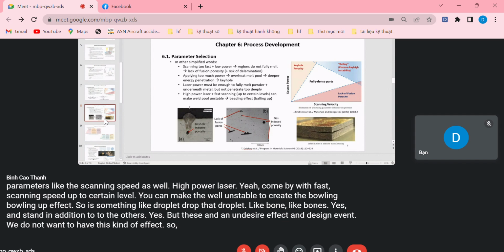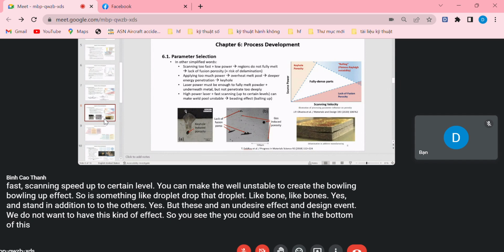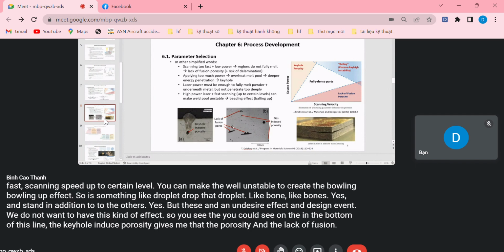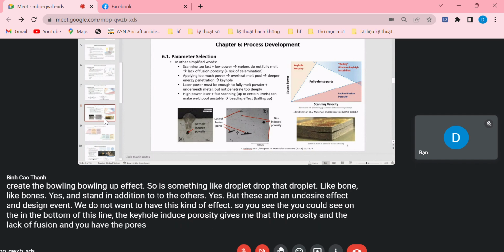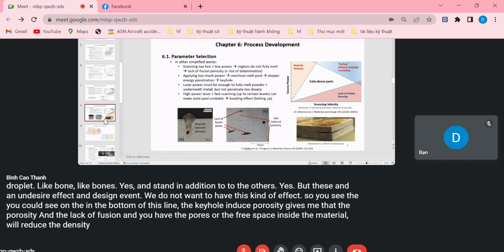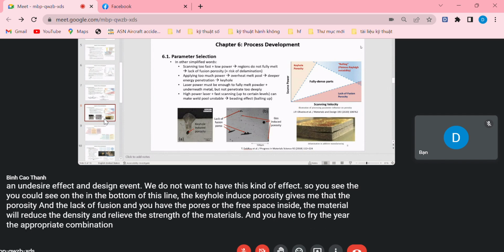You could see at the bottom of this slide the keyhole-induced porosity, which means the porosity and the lack of fusion, and you have pores or free space inside the material, which reduce the density and reduce the strength of the materials. You have to find the appropriate combination of different parameters in order to avoid these negative effects.